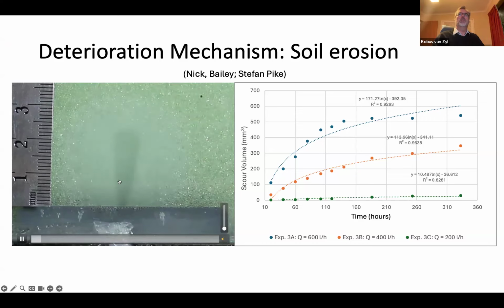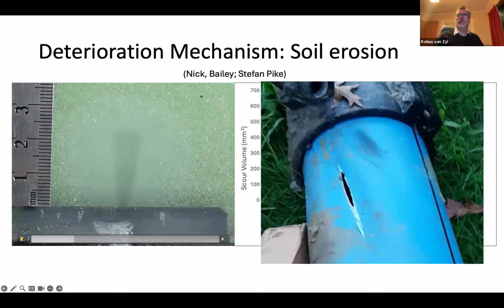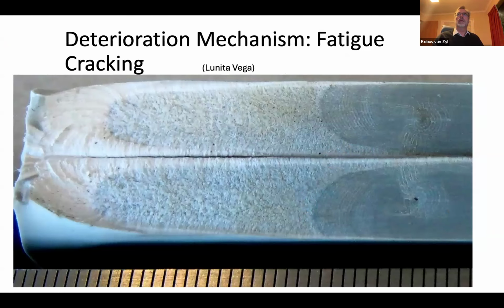So there you see the movement of the sand particles, the local fluidization, and the scouring of the surface of the pipe there. And you see this on pipes from the field. This is a collar that had a leak at the seal there, and you can see the hole that it's scoured there. And so this is affected by pressure because pressure affects the flow rate, and that drives this mechanism.